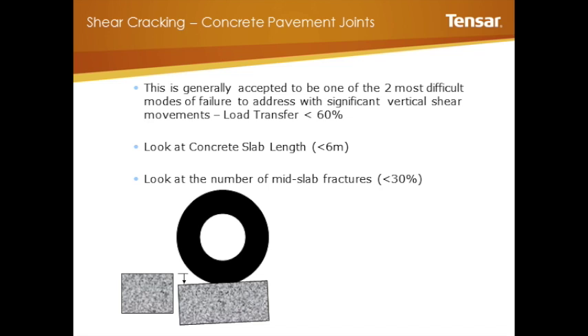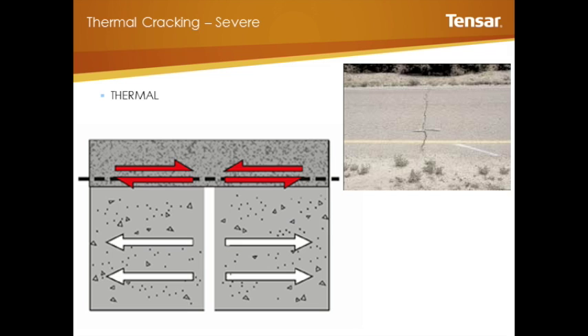So the next criteria we look at is the number of mid-slab fractures that you're experiencing. And we typically say that if the number of slabs with mid-slab fractures, out of the total length, is less than 30%, then we are still in a reasonable range of level of serviceability. But anything greater than that, we start recommending that some form of measurement takes place before you start spending money or investing in interlayer systems to assist you with this. So this ties in very nicely with the criteria that is used by AASHTO, but we feel that these are good boundary conditions or assessment techniques for you to adopt. All right.